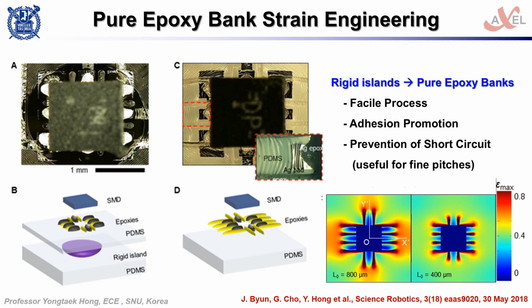Therefore, we additionally print pure epoxy bank in between for short circuit protection, and its thickness promotes adhesion of ICs to the stretchable substrate. We found that elongated and pre-designed patterns of the pure epoxy banks provide the same effects as the rigid islands in terms of strain suppression, as shown in these slides. Therefore, when more complicated routing of numerous chips is required, the pure epoxy bank structure is very useful.